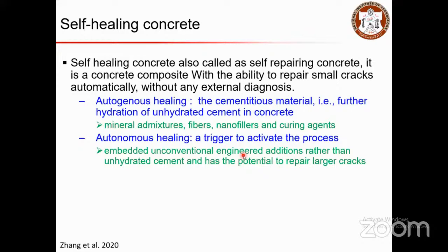There are two types of healing. One is autogenous, another one is autonomous. When I talk about autogenous, it is about the inherent ability of your material to do healing on itself. So when you talk about the cement, not all the cement particles will get completely hydrated when you do the process. There will be some unhydrated particles also. So when you have a crack, and the unhydrated particles are exposed to the region, and especially if there is water, they tend to react and then form further gels to fill up the crack. So that comes under the autogenous healing.